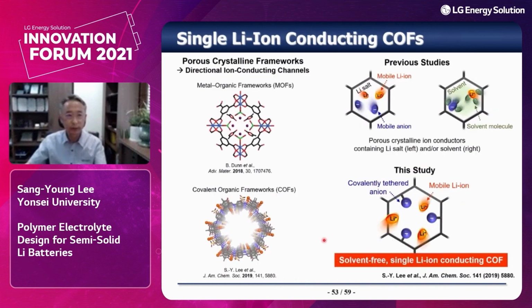Our last approach is the COF. The porous crystalline frameworks represented by the MOF and COF have garnered significant attention. In our case, we have designed a solvent-free single lithium-ion conducting COF. Here the anion was covalently tethered into the framework, and there is no solvent. Only the cations are allowed to move through these COF channels.